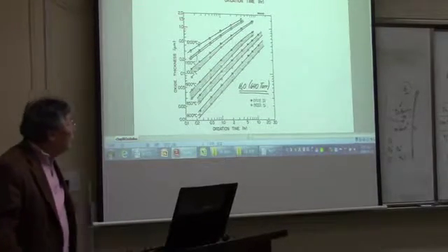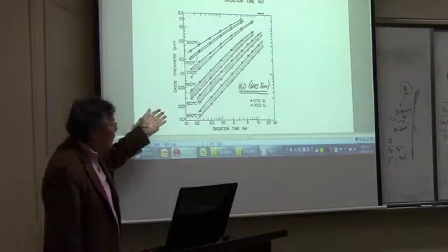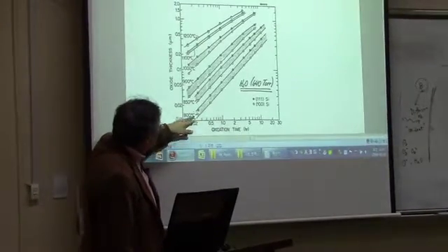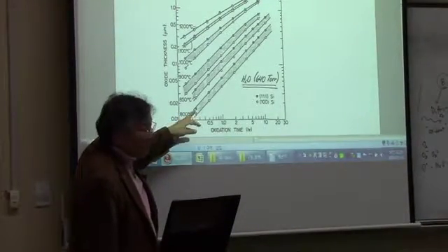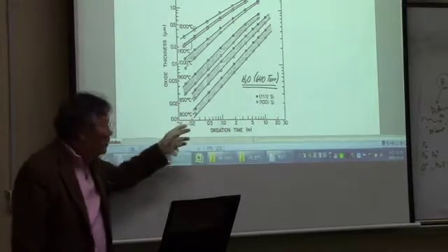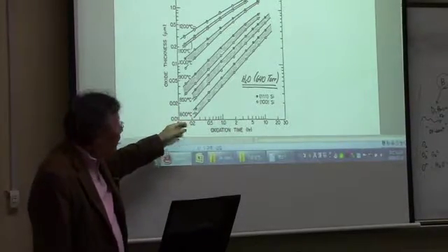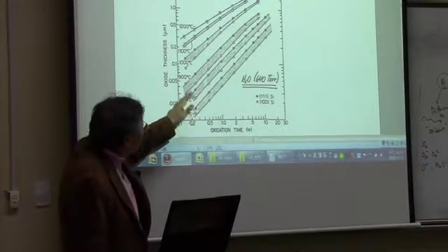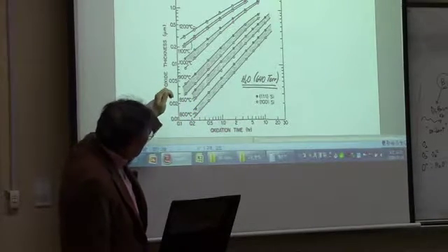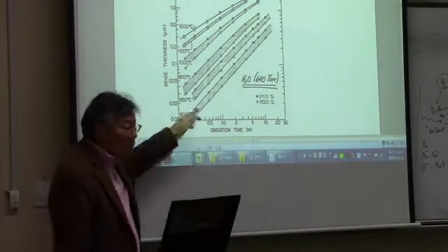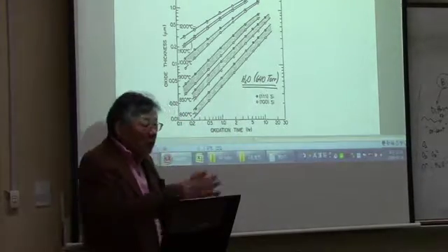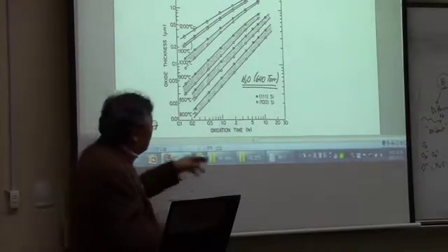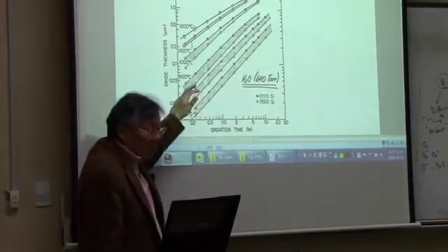And it's the same in the case of wet oxidation. In the wet oxidation case, the sensitivity to the temperature is not that great, but you do see that as you go down to the low temperature, the gap in the oxidation rate between the different crystallographic directions becomes larger and larger.